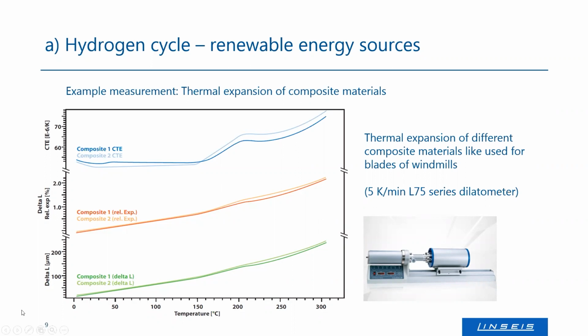And what we did was just expansion measurements. So we measured the expansion during linear heating with 5 Kelvin per minute on a standard dilatometer, and we found that at around 200 centigrade and at around 150 centigrade, there are two little phase transitions. You can hardly see them by eye if you just look at the absolute expansion, which is the green curve down here. And even if you look at the relative expansion, the red and orange curves in the middle, you see that there is a little bending and a little change in heating rate.